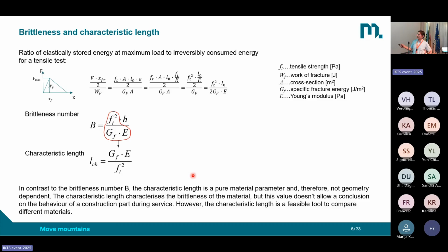You see, if the tensile strength is increased, then we have more brittle behavior. It's even much more brittle because it's squared. If we have a higher work of fracture, then we have a less brittle behavior, so the fracture is more stable. So from these calculations, in the literature the conclusion was to calculate the brittleness number B like this, with the tensile strength squared and a geometry parameter. For a tensile test, it would be the length of the test, divided by the specific fracture energy multiplied with the Young's modulus. And as you see here, there is the length of a sample. This means it's not a material parameter. It depends also on the size in the application.